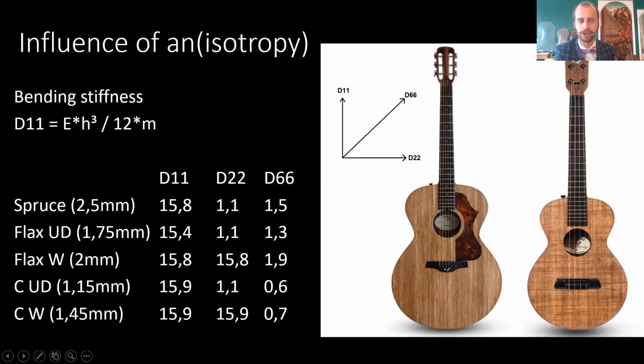So for example, if we take a spruce plate of 2.5 millimeters, and we calculate the engineering constants, we have this. So very stiff in the longitudinal direction, the D11, and a lot less stiff in the transverse direction, which is this, and then also in twist. So D66 is actually torsion. So if we take a plate like this and we twist it like that, that's actually this D66.